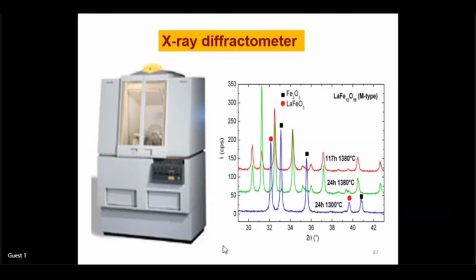So if you see first, second and third, what is different? In the third case, there is no alpha Fe2O3, which is a non-magnetic phase, and there is even no LaFeO3. So they have just refined the method and found the phase purity of the sample just by increasing the temperature as well as the number of hours, that is the sintering time. So it's very important.